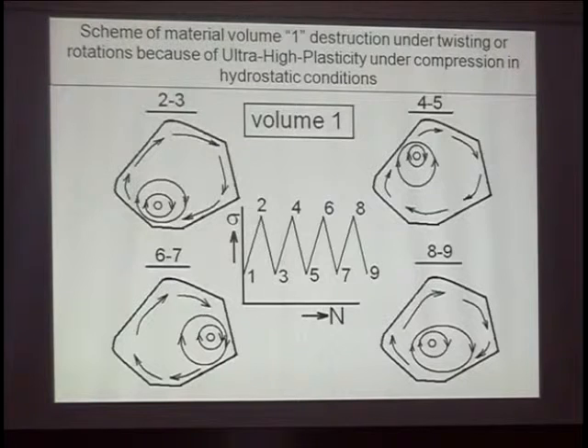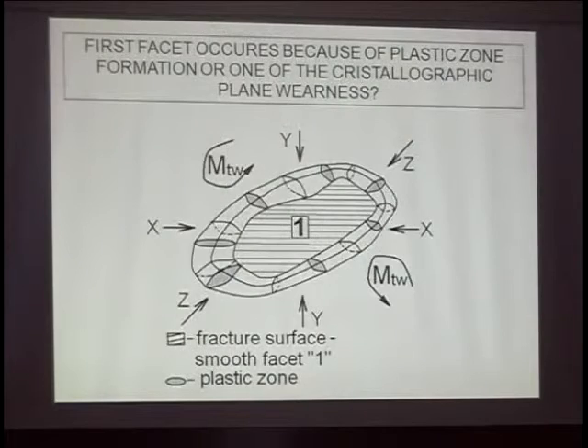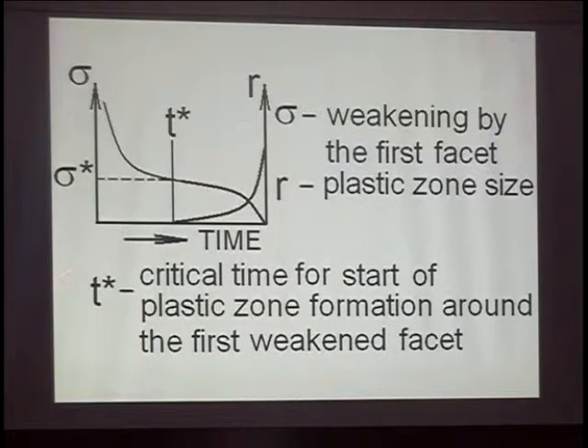But there exists only one question: what is first? First, material weakness, then plastic zone formation around this first facet, or maybe they exist simultaneously: there is weakened material and there is also formation of a plastic zone. We think that the plastic zone around this first facet forms after some weakening of material. So in our model, first of all there is weakness at one of the facets of material, then formation of the plastic zone size, and then we can see crack propagation.